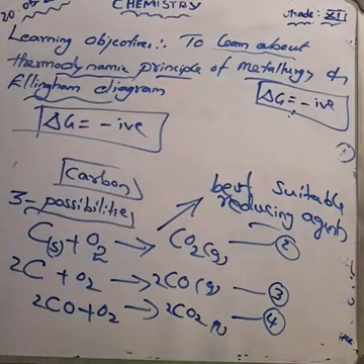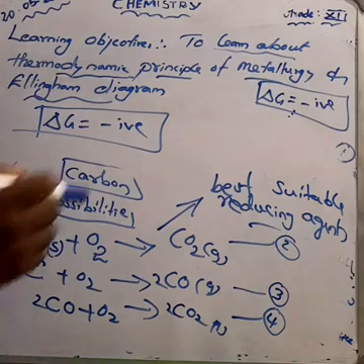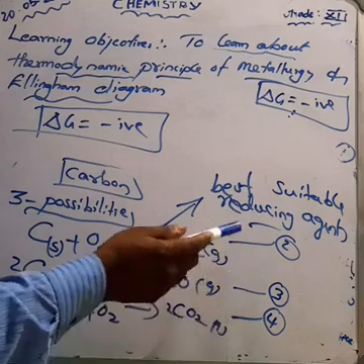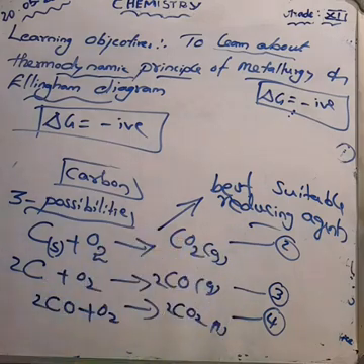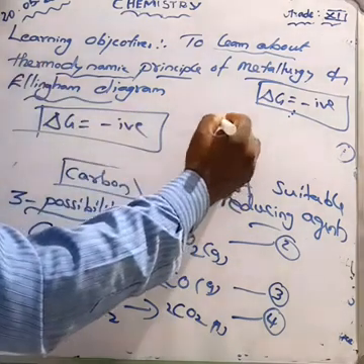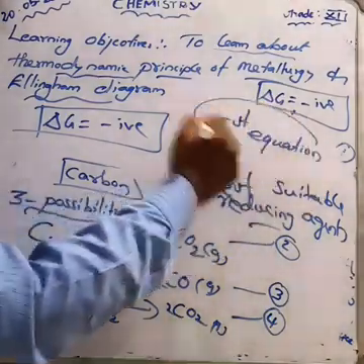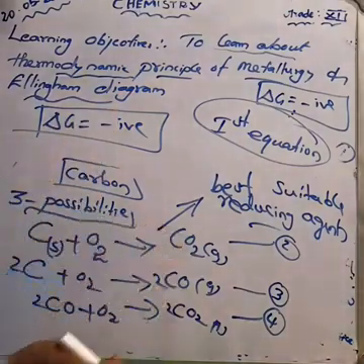Therefore, thermodynamically, the reduction of metal oxide, that is the first equation, where metal oxide is converted into metal plus oxygen, with the given reducing agent, maybe the reducing agent may be in equation 2 or equation 3 or equation 4, can occur if the free energy change of the coupled reaction is negative. Listen all of you, here for the metal oxide we have to use one reducing agent, and this reducing agent may be in the second equation, the third equation or the fourth equation.